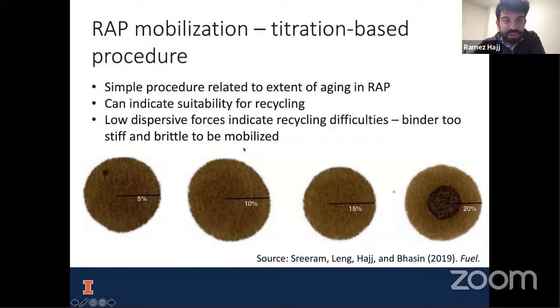So the idea is that you titrate this small specimen with something that dissolves asphalt. And when you see solubility, you understand how much solvent it takes to dissolve this material, or how much dispersive force this material has. So we can easily convert this to the amount of dispersive forces present. And if the material is not very dispersive, that means it might create recycling difficulties because the binder is too stiff and too brittle to be mobilized. So we predict that this may lead to difficult binders to recycle.